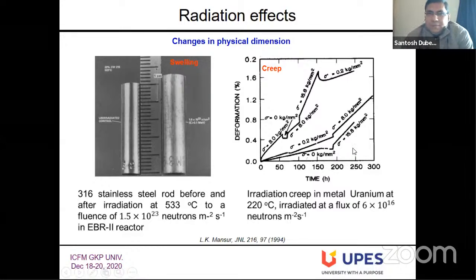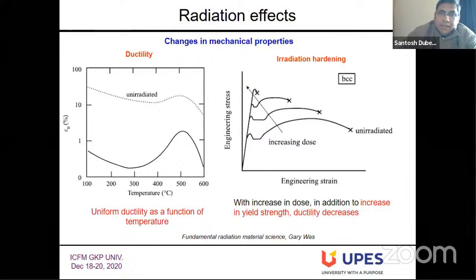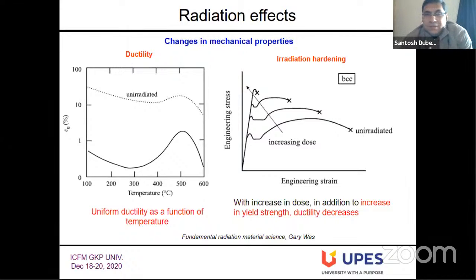Similarly, creep deformation is also very important, especially at high temperature. Creep deformation is very prominent, and this is an unwarranted thing, especially under radiation, because we have a non-equilibrium concentration of defects. The rate of creep becomes really high. You can also see a loss of ductility in the materials.